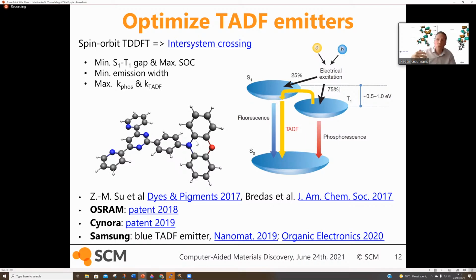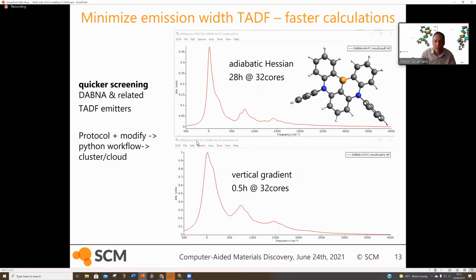Now there's a recent class of these TADF emitters, the DABNA. They typically have a boron atom centrally, bonded to nitrogen atoms. They tend to have very narrow emission profiles, and if you remember the range on the one I showed for the platinum, you can see indeed they are very narrow emitters here.